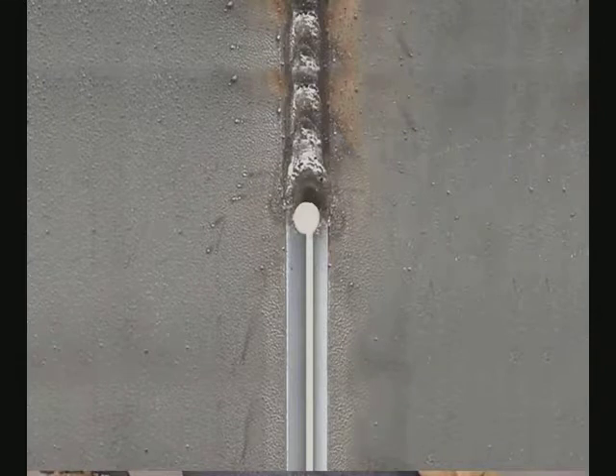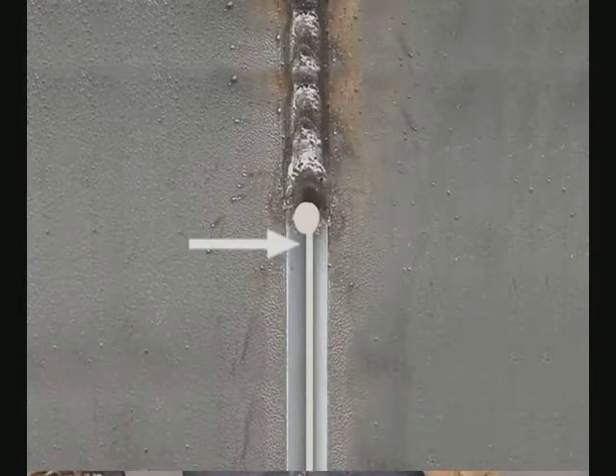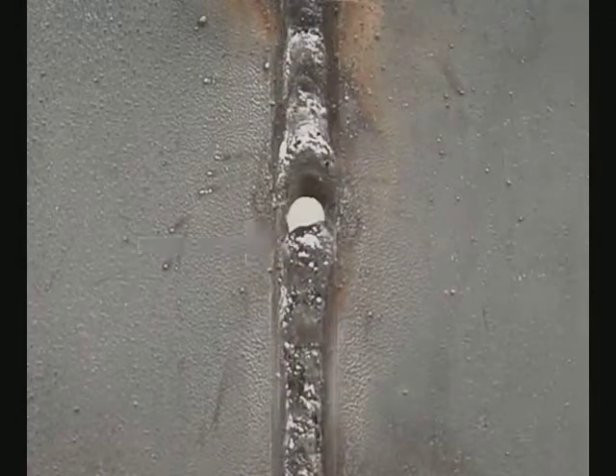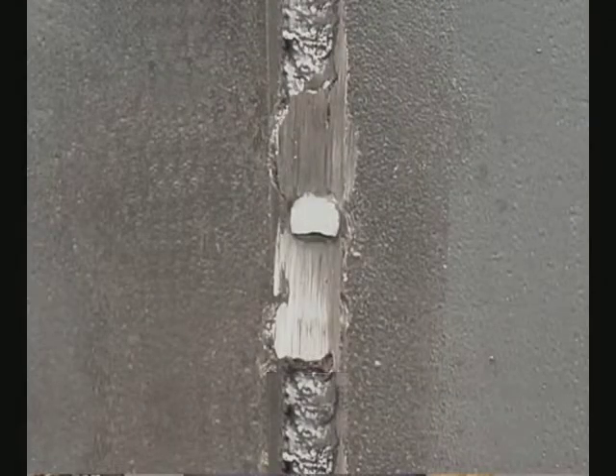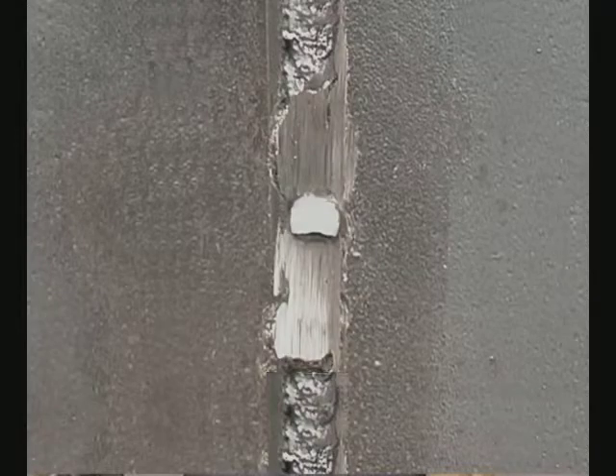If you do open a hole, stop right away, pulling the rod back over the bead. Restart right at the edge and keep going. When you finish the weld, grind the edges thin on both sides of the hole and fill it in.